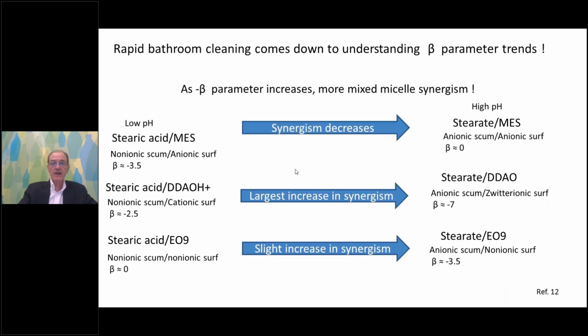Well, what we realize as surfactant scientists is what cleaning the bathroom amounts to is understanding mixed micelle synergism or beta parameters. So for the stearic acid MES system at low pH, we have a non-ionic scum, stearic acid, interacting with an anionic surfactant, MES. And beta parameters for such systems are known and measurable, and they're about minus 3.5. But as we turn the pH up, we are actually decreasing the synergism, because at high pH, we actually have an anionic scum interacting with an anionic surfactant.